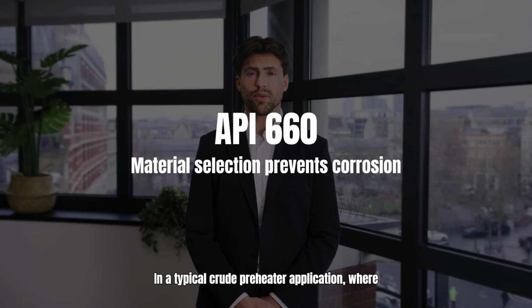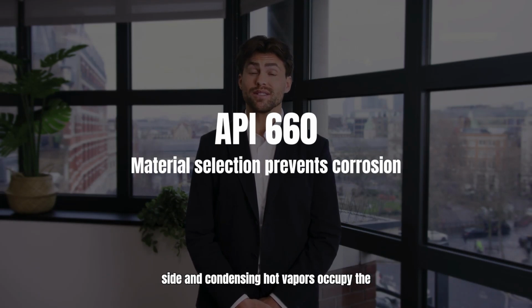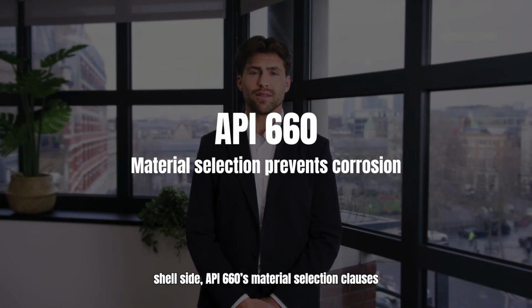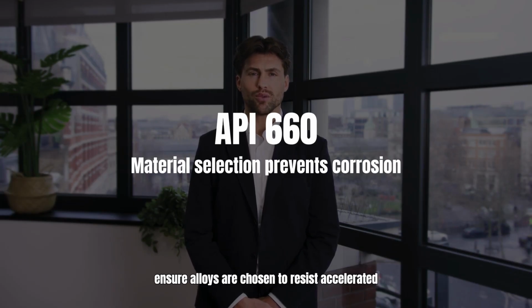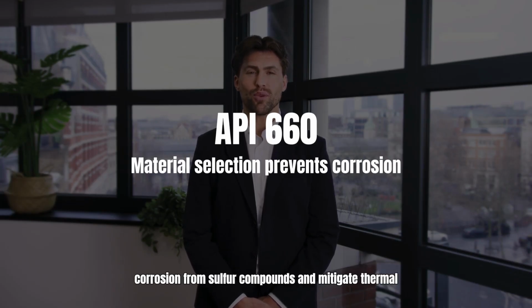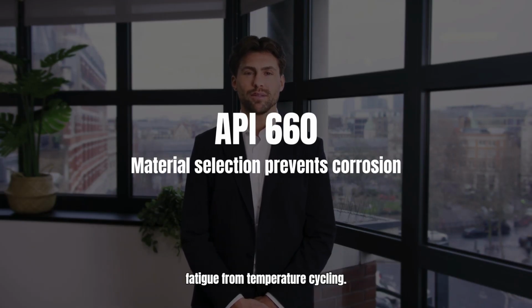In a typical crude preheater application, where high-temperature crude oil flows through the tube side and condensing hot vapors occupy the shell side, API 660's material selection clauses ensure alloys are chosen to resist accelerated corrosion from sulfur compounds and mitigate thermal fatigue from temperature cycling. For a cooling water exchanger handling aggressive seawater on the tube side, API 660 explicitly requires proven pitting-resistant alloys like 90/10 CuNi or super duplex stainless steels to prevent localized pitting corrosion that could perforate tubes prematurely.